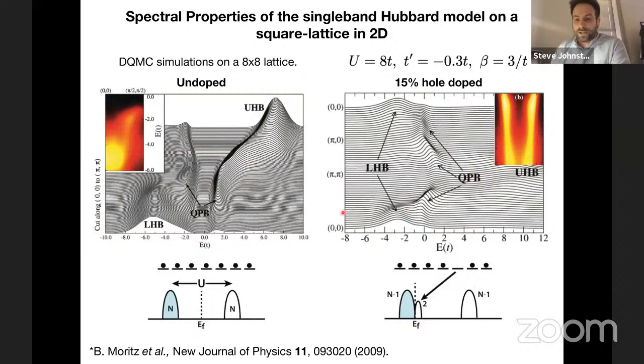So, this calculation, not surprisingly, confirms the spectral weight transfer picture. But the other thing I want to point out is that this quasi-particle band actually has a dispersion associated with it. And the dispersive properties of this are really inherited from the underlying non-interacting band structure, right? It's determined by a renormalized t-t' band structure in the calculation. This is going to be important a little bit later when we start looking at the quasi-particle interference.